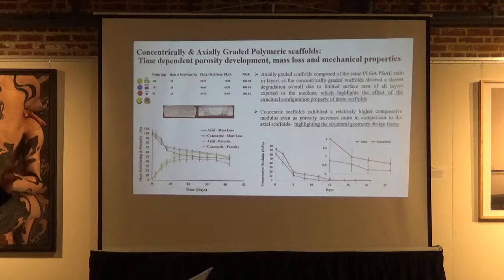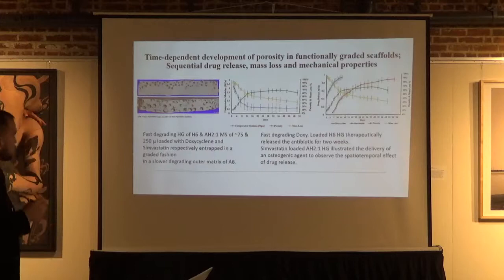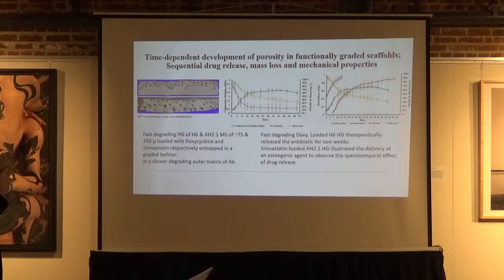Moving on to this slide, it shows the time-dependent development of porosity. This cross-section micro-CT image here was taken 4 days after degradation, and you see just the porous structure of the top layer. The bottom image shows after 10 days, so you have that spatial-temporal effect with these scaffolds.